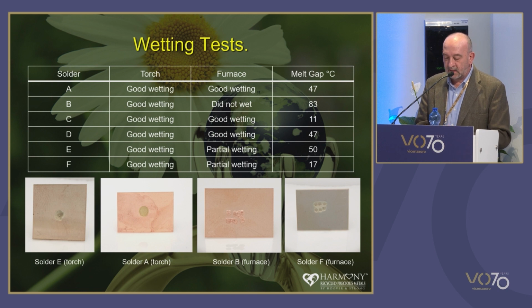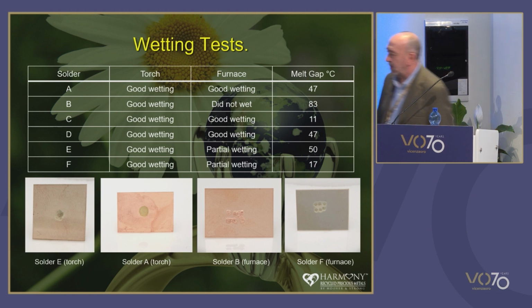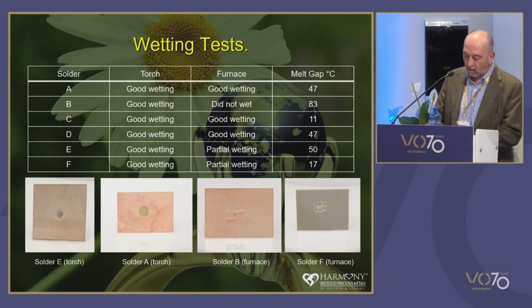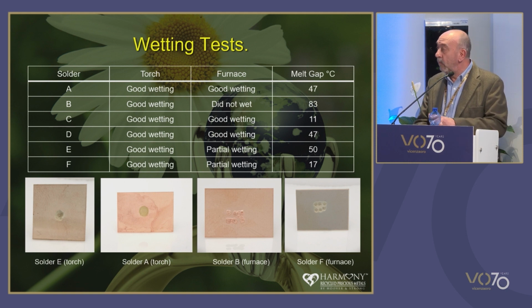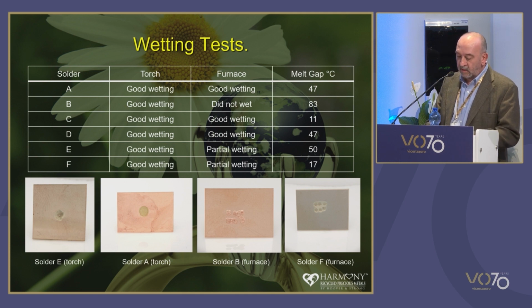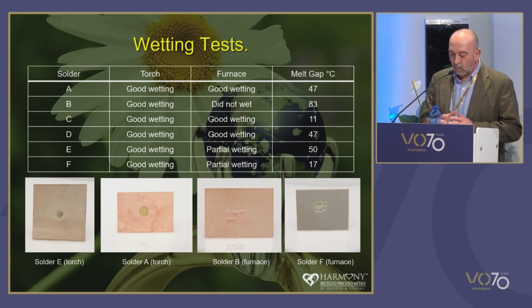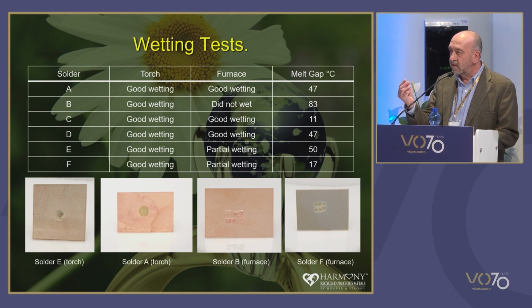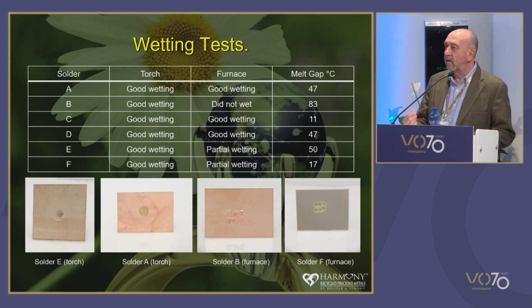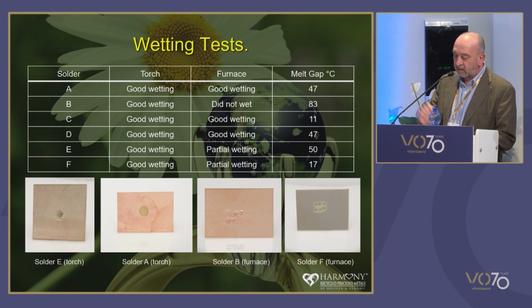Solder B in the furnace test was by far the worst result, and there seems to have been some liquation of the pieces, but no discernible solder flow and no wetting on the sheet. I think at that point, it looks horrible. Solders E and F, the white gold solders, showed signs of some wetting in the furnace tests, but again, we could see some of the residual solder pieces in there. So the furnace results may be exhibiting a phenomenon where diffusion of the lower melting point constituents in the parent metal raises the flow temperature of the solder remaining in the piece to a melt point above the set temperature of the furnace. So the remaining solder doesn't melt.